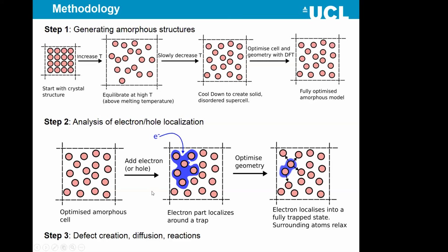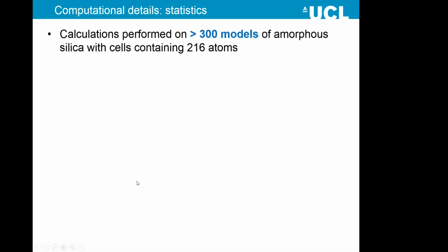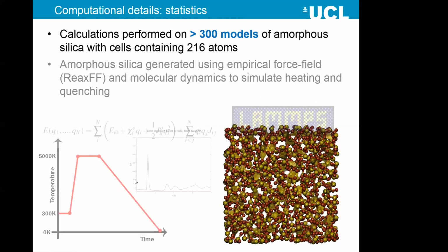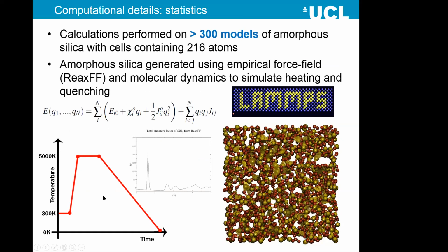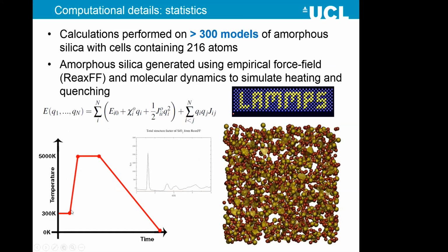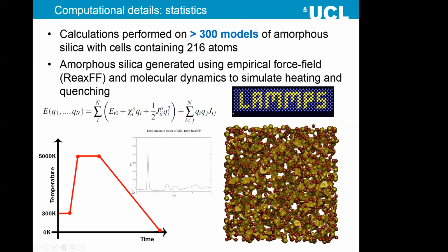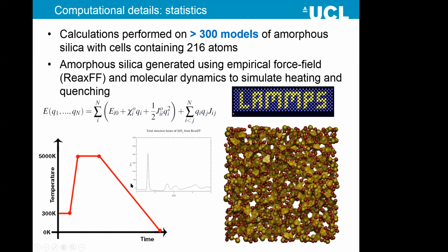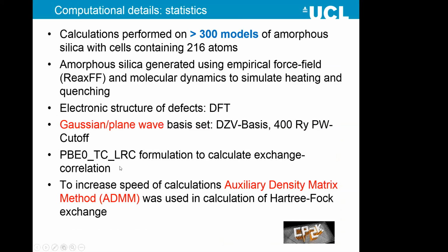Again, very similar to what Jochen has been talking about. So these electrons may be delocalized, or they may localize and form some quasi-polaronic type of states, and then get trapped inside this oxide, and that is bad for performance of the device. So to do that, we use molecular dynamics, mainly using LAMMPS and various force fields, ReaxFF. And so we, first of all, study the properties of these amorphous materials. And then when we have defined their properties, we put them into CP2K in this case.